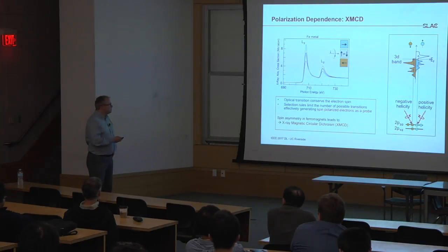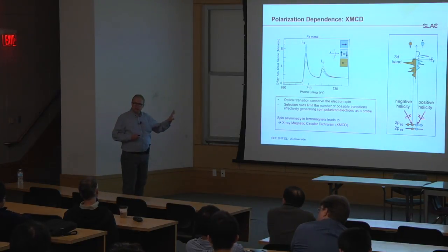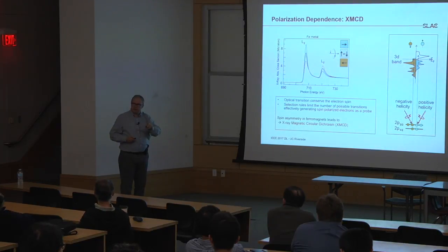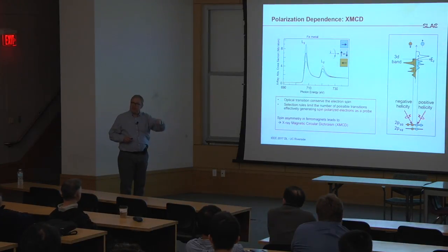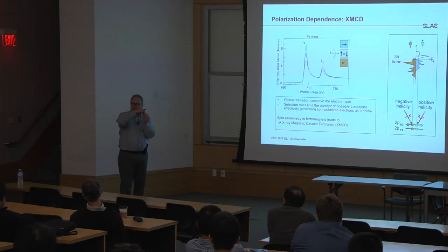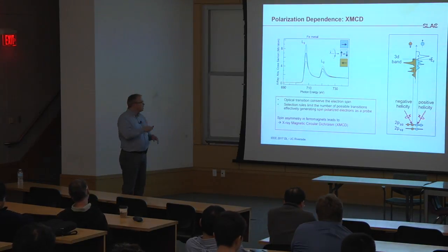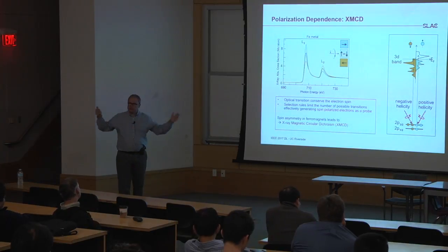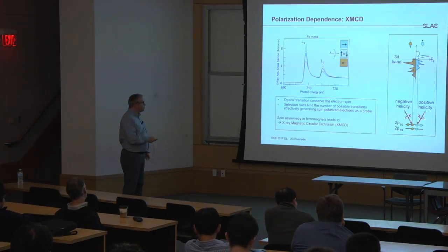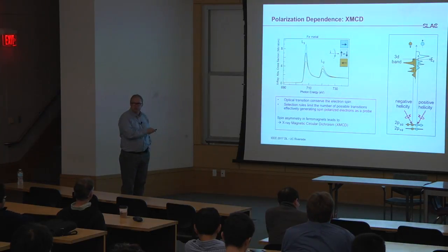For example, in copper, that's a little tricky because the spin polarization that you excite is actually in the S states. Since there's a strong hybridization between S and D, you actually can't see this. Let's say you have a spin polarization in the S states, but you excite into the D states, you will not see that spin polarization. Does this answer your question?